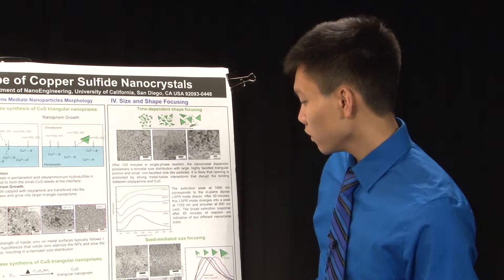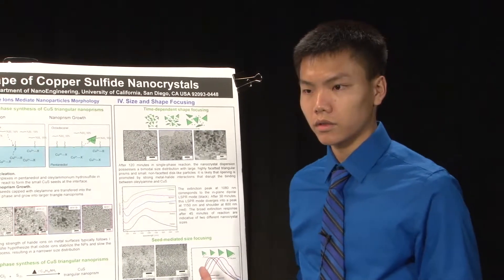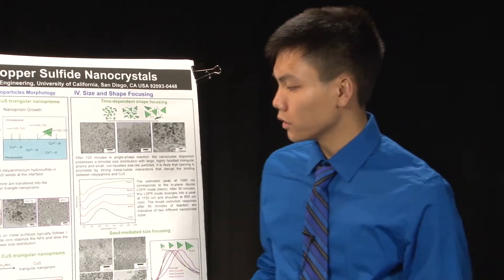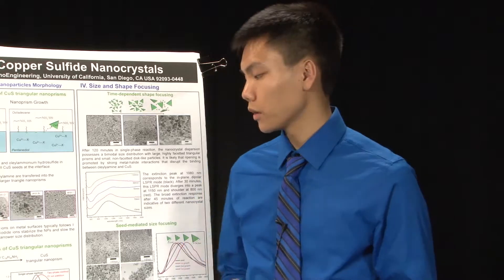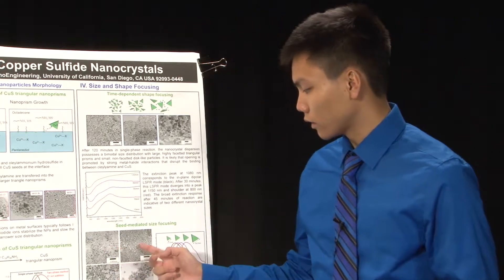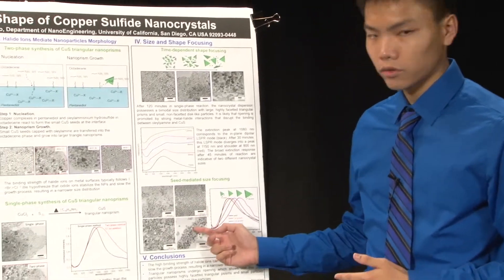The next step we tried was a seed-mediated synthesis, which is similar to the single-phase synthesis. First we produce the seed particles, and then for each growth step we do the same reaction, but add in the seed or previous growth particles to see them grow larger and larger. As you can see here, this is the seed, then the first growth, second growth, and third growth.